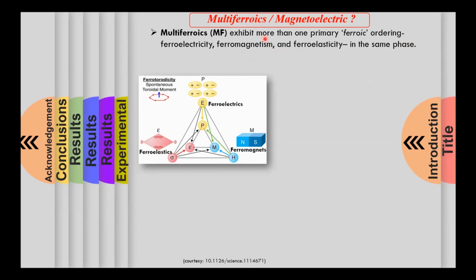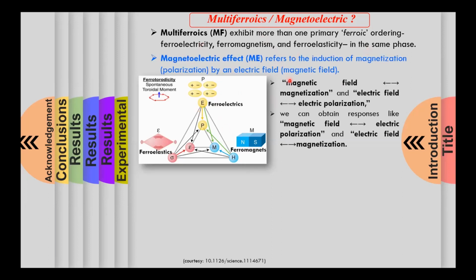One of the most appealing aspects of multiferroics is the coupling between these order parameters. For example, coupling between magnetic and electric polarization leads to the magnetoelectric effect that refers to the induction of magnetization by electric field or the induction of polarization by the magnetic field. So here we need to see that if I have simply a ferromagnet, then the magnetic field controls the magnetization. And if I simply have a ferroelectric, it's the electric field that controls the polarization. But when we have a multiferroic that couples ferroelectricity and ferromagnetism, then the magnetic field can control polarization and the electric field can control the magnetization. So this is the beauty of magnetoelectric multiferroics.